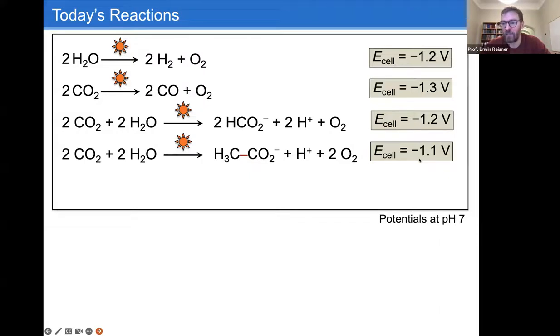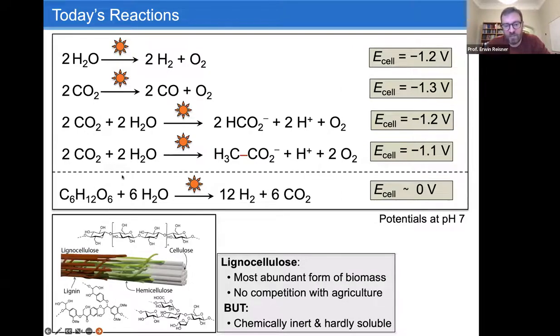And these are cell potentials at pH 7. And you can see they're all endergonic, so with a significant positive Gibbs free energy. But ultimately, the energy requirement is quite similar. So if I talk later on about the solar panels, you will see that always when we discuss chemistry that's coupled to water oxidation, there are two light absorbers to make sure we have enough driving force for efficient reaction rate in this case.